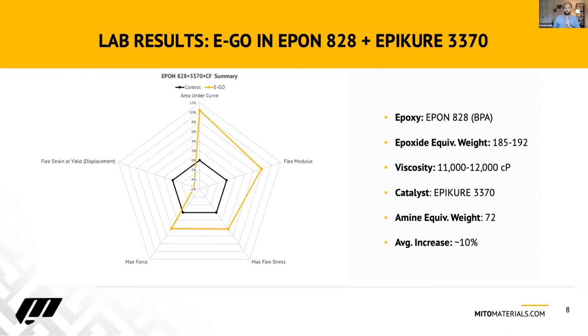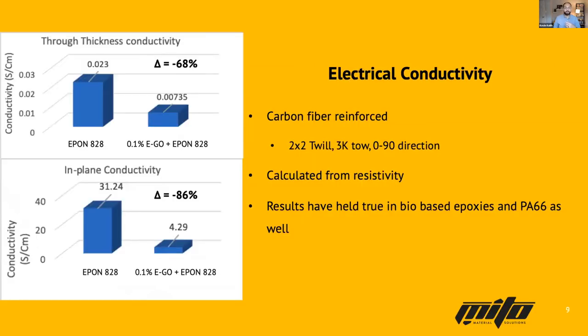Now, with, of course, EPON 828, that is a very, very base material. And so we see these single double digit increases here, but whenever we put it out into the field with customers, whether it's polyester, vinyl ester, or other types of more complicated epoxies, these results drastically increase. And that's because they have more functional sites to grab onto, those esters and all that type of stuff.